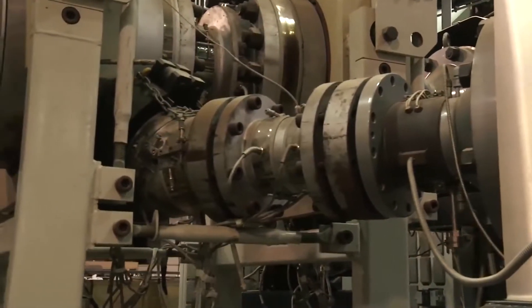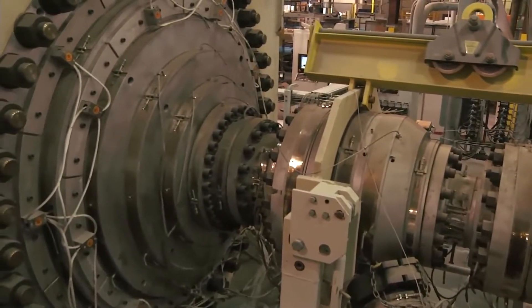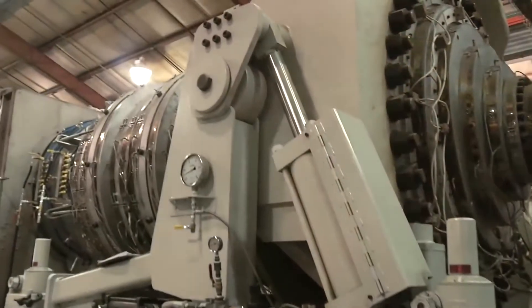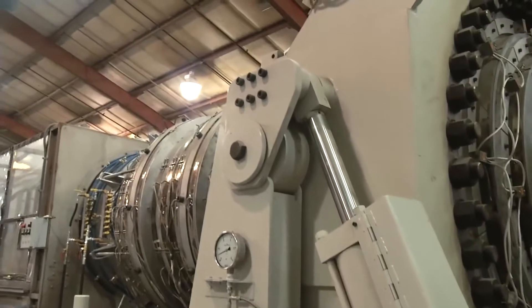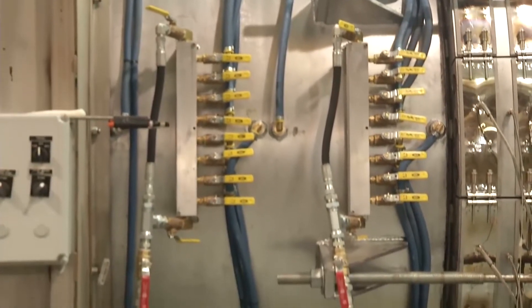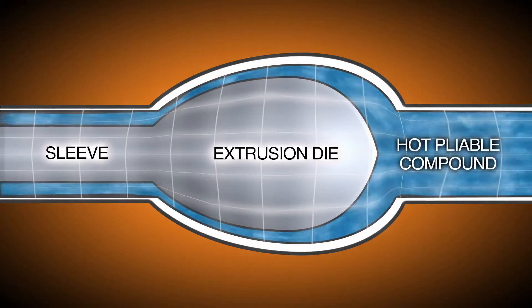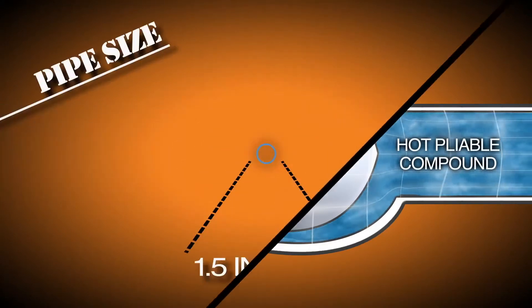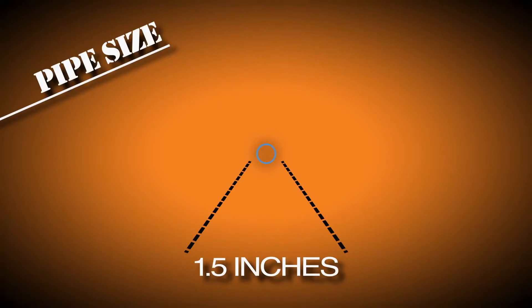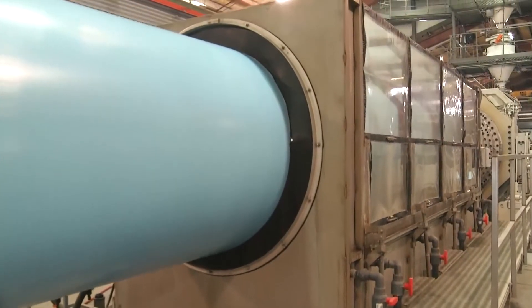The proper application of pressure and temperature turns the compound into a hot, pliable material suitable to push through an extrusion die into the desired size of PVC pipe. The die consists of several components held at precise temperatures above 300 degrees Fahrenheit and culminates in a sizing sleeve, which determines the outside diameter of the pipe. As the PVC exits the sleeve, the thickness of the pipe wall is determined by the speed the pipe is pulled from it. This controls both the inner and outer diameter of the pipe and wall thickness to match specific industry standards. A solid wall pipe from Diamond Plastics can range from 1.5 to 60 inches in diameter, which is the largest solid wall PVC pipe made in the world.